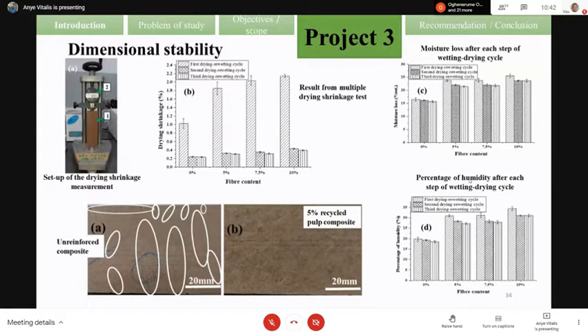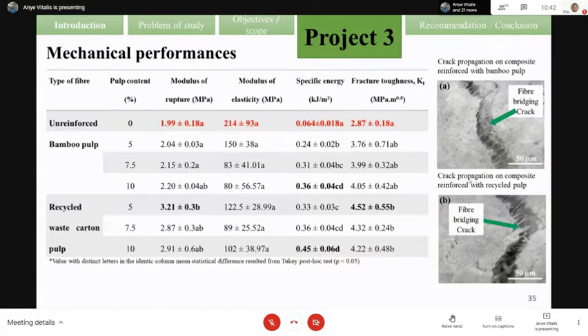We study the surface of the fiber, the unreinforcing and reinforcing fiber. We realize that there was presence of cracks on the surface of the unreinforcing fiber, which is showing that during the shrinkage there is some crack propagation, but the fibers were helping to reduce the crack propagation. So we study also the mechanical performance under three-point bending system, and also the fracture toughness.